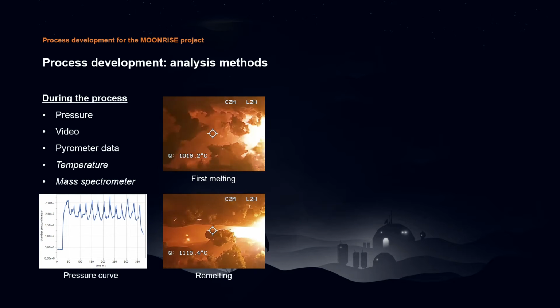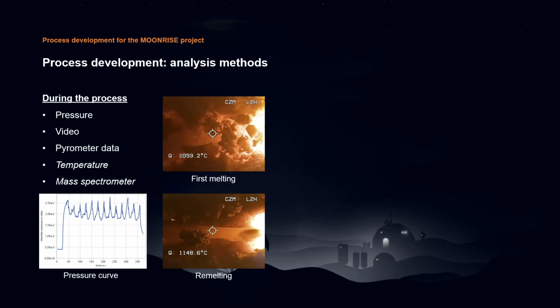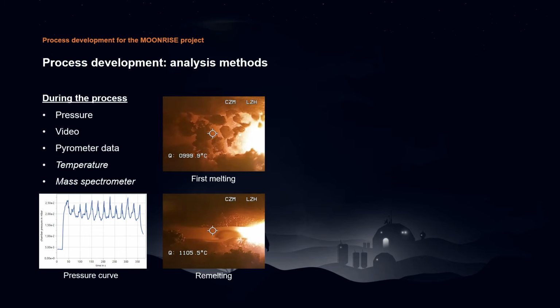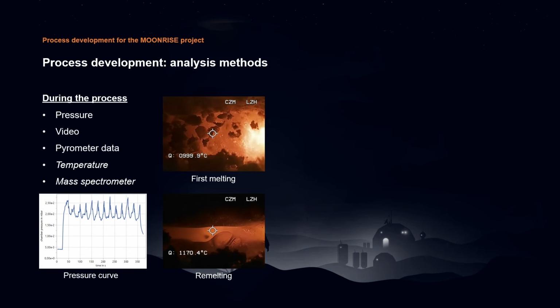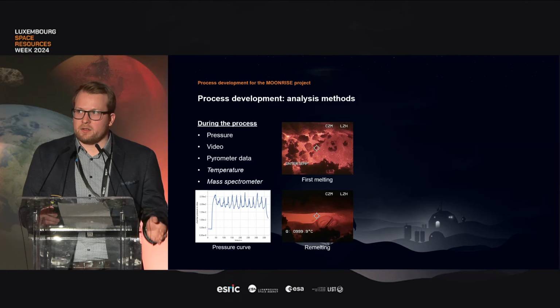And in these videos, we can see how the melt pool is behaving. We can see how the size is developing. We can see the pores moving. And we can also see, especially in the top one, how there are some unmolten particles sprayed on the melt, which leads to this bad detectability.